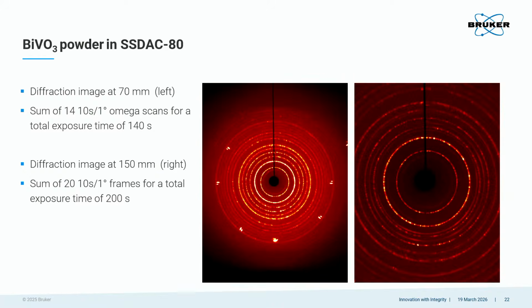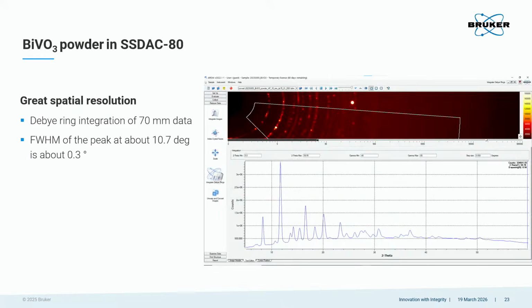Yes. And what you see here is a good example of what people were after in this experiment. The image on the left was collected at 70 millimeters, and the other one at 150. What you also see is that, because amorphous scatter falls off with R squared, at 150 you not only get a better separation of the lines, but you dramatically cut down on the amorphous scatter. So you're telling me that the right one is also in the diamond anvil cell? Yes. Wow. That is because of the background scatter, like you said.